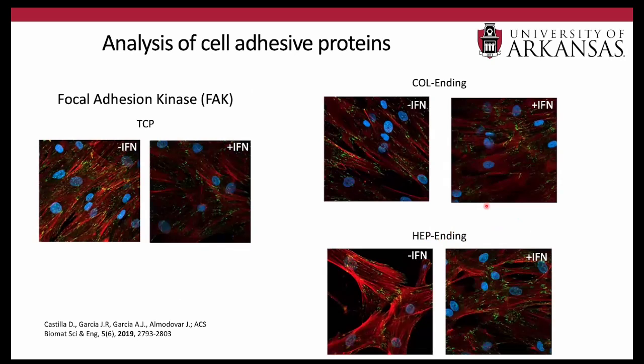So we did some more studies. We did an immunofluorescence analysis of the focal adhesion kinase. So this is an important receptor in the cells that is involved in cell adhesion. And at the beginning, we saw that really there's no difference in the expression of this kinase in the presence or absence of the growth factor or on the different surfaces. So in the images here, the expression of the kinase is the green dots, whereas the blue is the cell nucleus and the red is the cell cytoskeleton.